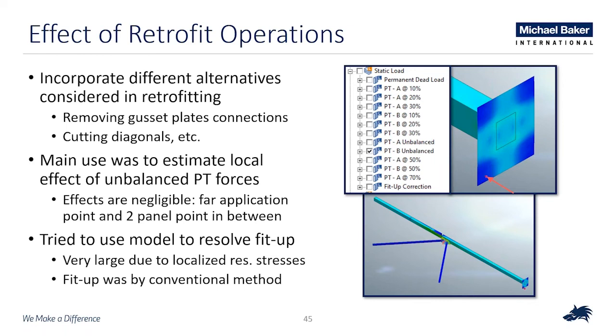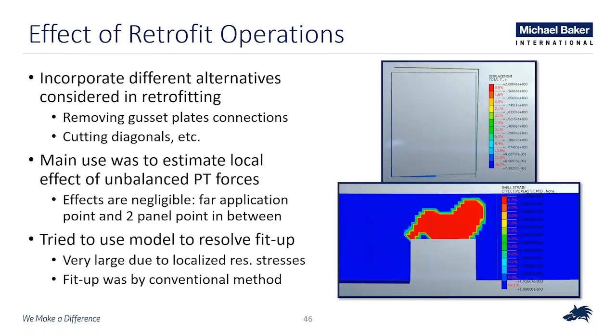The second use that we gave to this local model was to try to resolve the fit-up issue, a little bit of the fit-up issue that is encountered after the whole PT operation is completed. Well, the geometry of the tie itself was closer to our working objectives. There was still a little bit of distortion at the fracture location, as you can see in the top image. So there was a necessity to basically square that box.